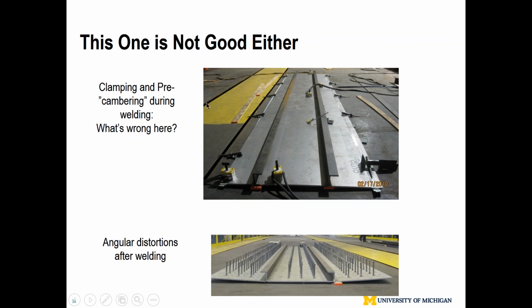Here I'm showing you an example. Obviously, this is from 2010, related to one of the manufacturing companies. So here I get angular distortion. How about I jam something up below the fillet weld, and then I do pre-cambering, essentially pre-bending, okay? But that did not work. After releasing the bending, you can still get the distortion. That means this clamping is not in the right location, too far away from the action zone. What is the action zone? The plastic zone, a couple times the weld width in this regime. That means you had to go in and clamp that area. Obviously, it's a little bit difficult.